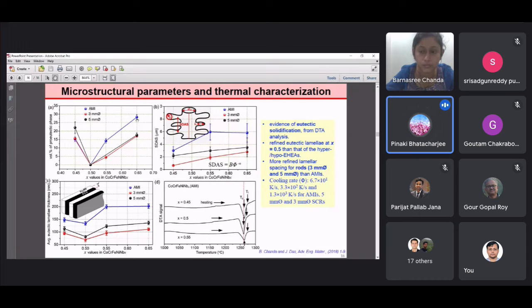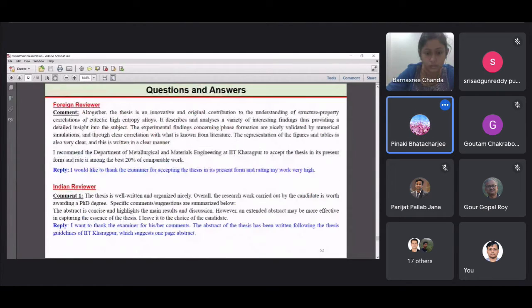In general, of course you can do hot deformation studies and so on. But this is a general comment on the thesis that tensile ductility, which is a challenge, probably cannot be achieved. Compressive ductility is not a problem because even in a brittle phase you can have compressive ductility, and even high temperature ductility is not a problem, but tensile ductility at ambient temperature is definitely more challenging with such a microstructure.